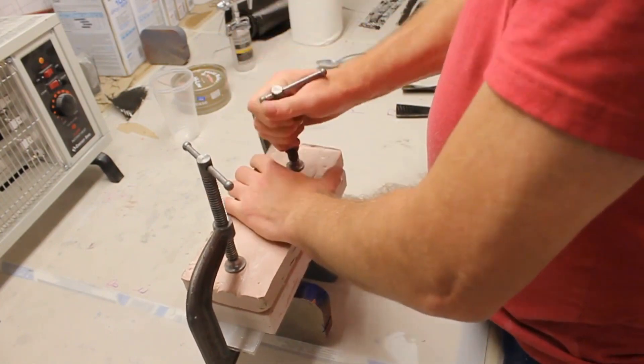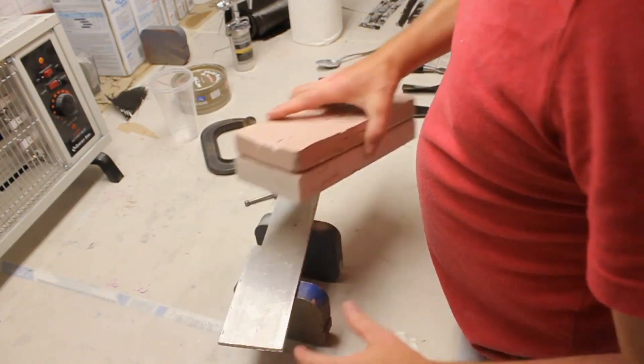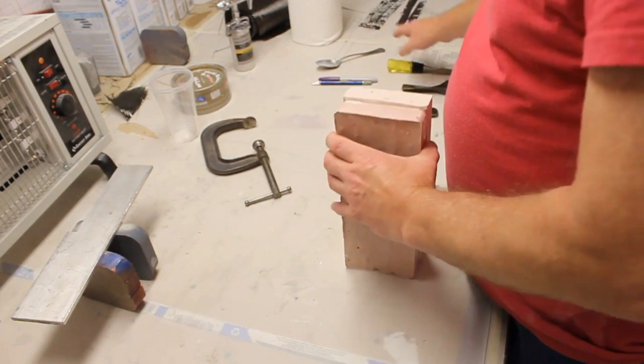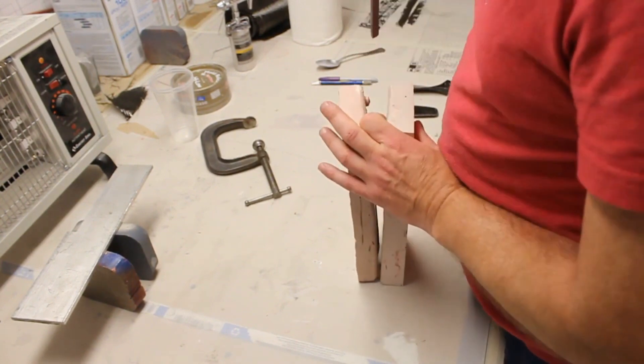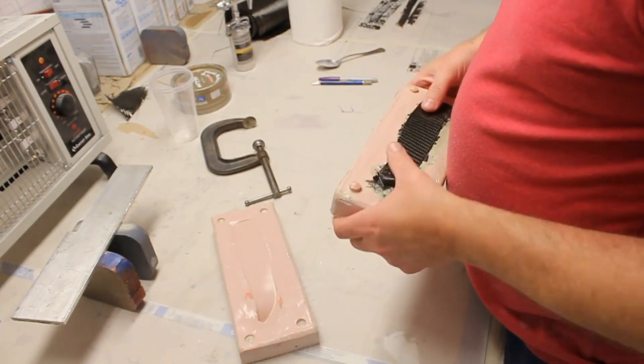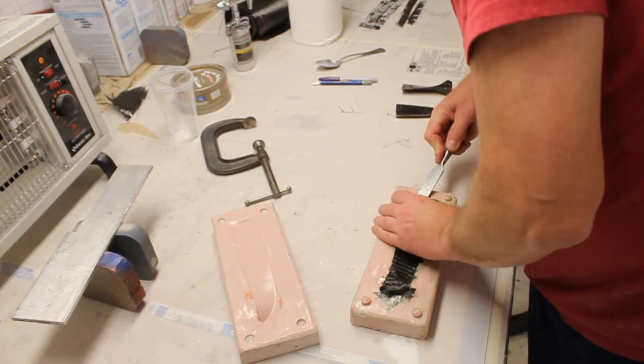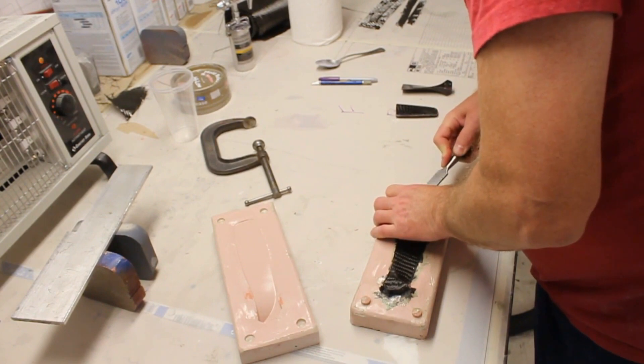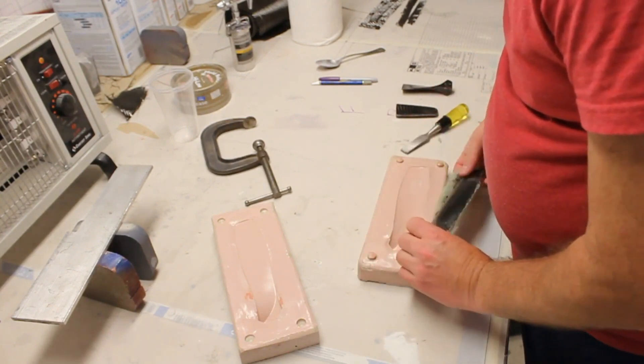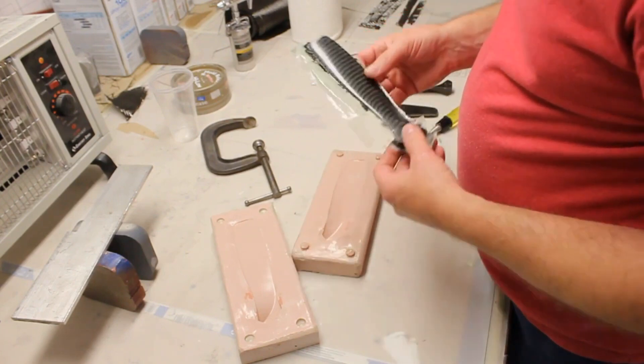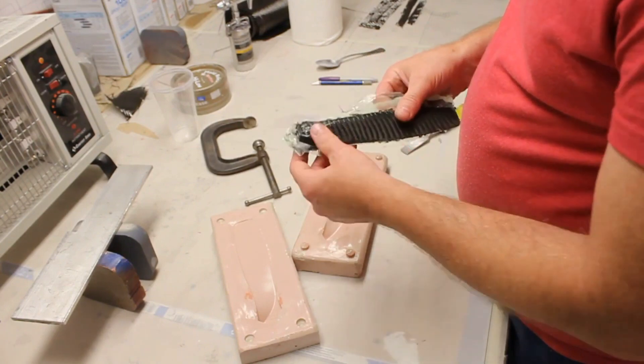Now what we're going to do is take the two parts of the mold apart and see what's going on inside here. If this worked right, it should pop apart and the part will look glass smooth. The mold will also look glass smooth where it popped out - it won't damage the mold at all. It takes a little bit of force to get this popped apart, but once it does, it just bangs and comes right apart. Here it came out perfect. You can see the shine in it. It's stiff. It's only cured about four hours and I did use the fast hardener. I'm going to pop the propeller blade out carefully just to make sure I didn't get any air bubbles anywhere. It looks really good - it basically came out perfect. You can see all the resin that squeezed out around the perimeter because there's actually an air bubble in the middle of that prop. It's air tight and hollow in there. That prop came out to be about 1.4 ounces and that's exactly what I was hoping - under 1.5 or 1.6 ounces.